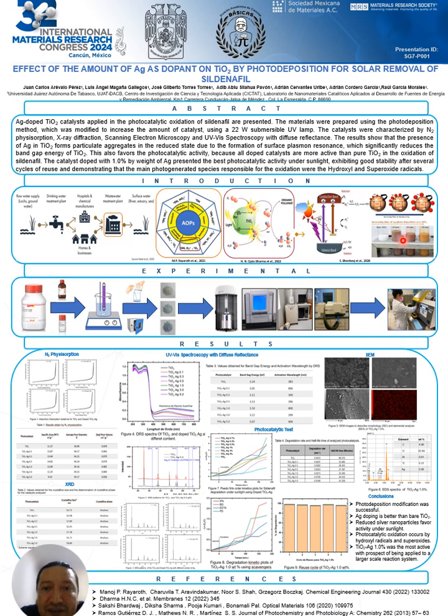Therefore, titanium dioxide doped with silver at different concentrations prepared by the modified photodeposition method is proposed here to evaluate the effect that silver has as a dopant on the photocatalytic oxidation of sildenafil under sunlight.